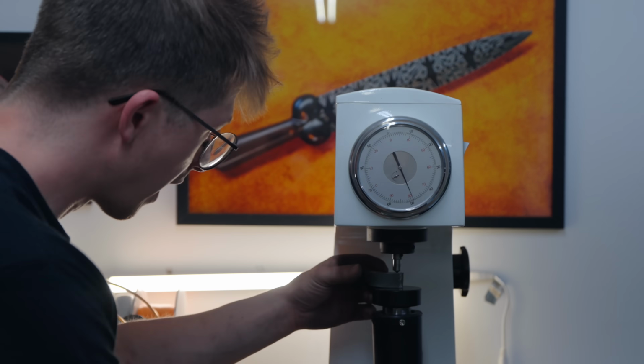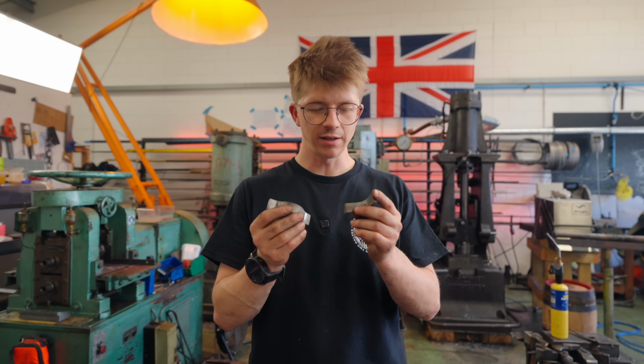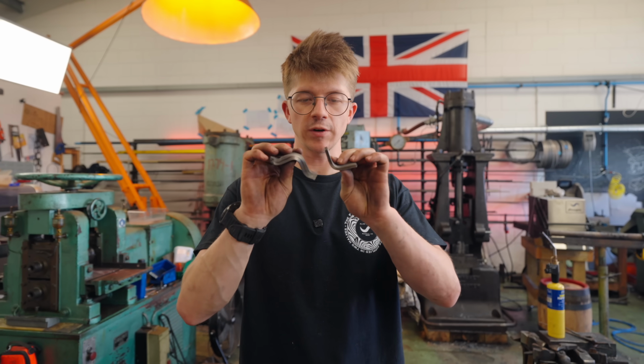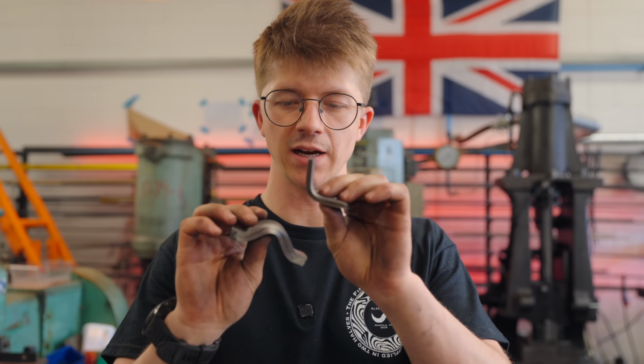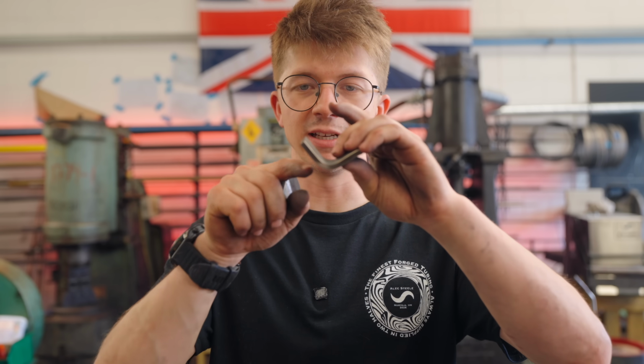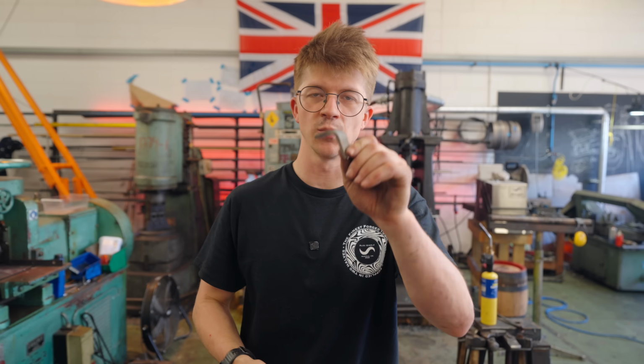That was 49 Rockwell, so a good bit softer than the previous one and not quite hard enough for a knife. Very interesting. These are, of course, very different cross-sections, this one being thinner than that. It means that the bend radius relative to its thickness is smaller or bigger? I don't know. But there's a difference. It takes less stress to bend a small thing than a big thing.